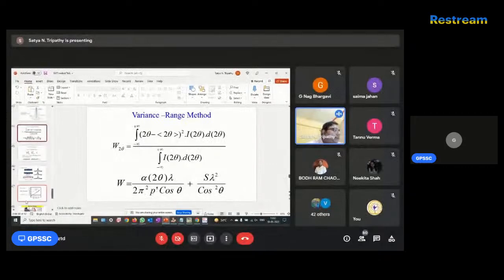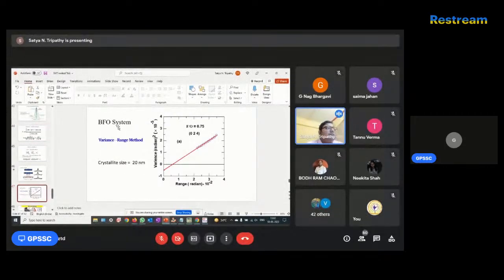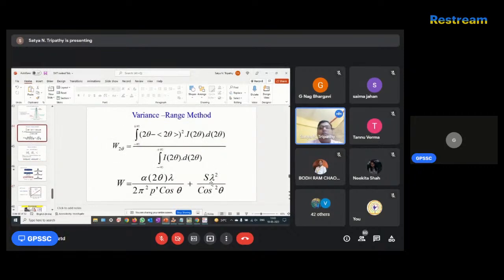I'll show you one graph I have. Yes, so this is a BFO based system. We calculated this using the variance range method. The crystallite size came up to 20 nanometer because it is a combustion synthesized sample, and this data has been reported in Materials Chemistry and Physics. We took one peak and analyzed the variance and range by employing these equations. You can also do that. This is a very good way.